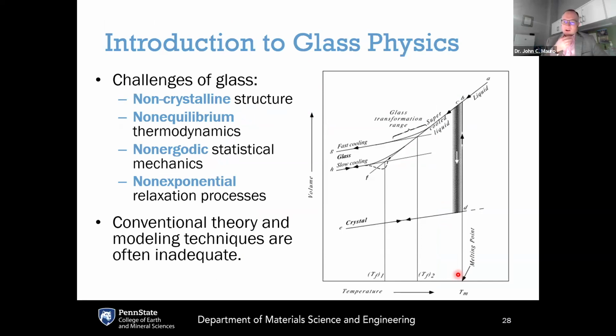It gets back to where glass comes from. So glass comes by cooling a liquid from a melt, where that melt is cooled so fast that it doesn't crystallize. The main physics behind glass is that if you start off in the liquid state, normally if you cool a liquid, it will crystallize. It'll undergo this first order thermodynamic phase transition as the atoms in the disordered liquid rearrange themselves into an ordered crystalline configuration and form a crystal.